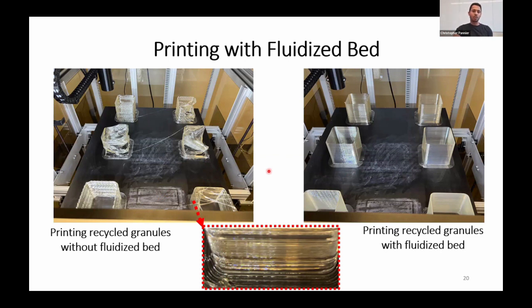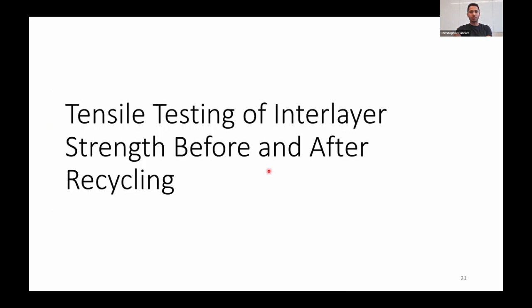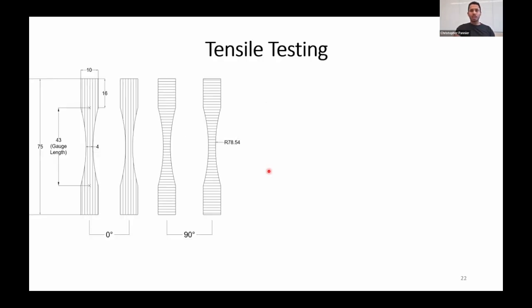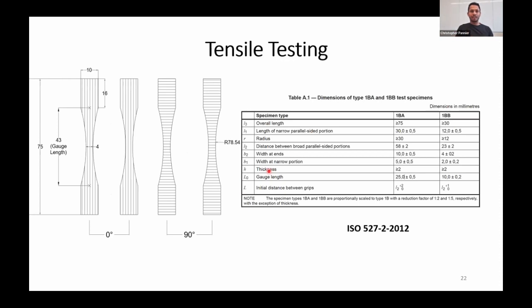So now once we had all of these printed successfully, we moved into the tensile testing to look into the mechanical properties before recycling and after recycling. First we wanted to have these dog bone shapes closer to a specific standard. So we used the ISO standard here, and it's very close to that standard in terms of the dimensions of the dog bone shapes.